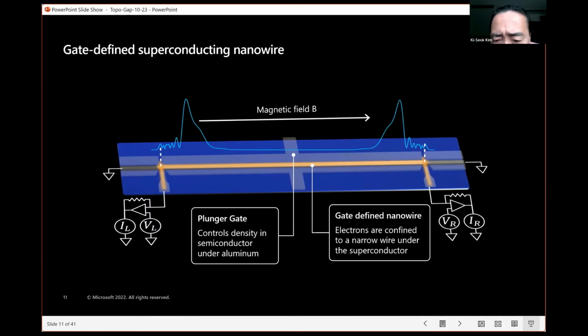Okay. Are there any questions so far? Yeah, elementary question. So I missed too. So superconductivity is assigned to aluminum. So applying gate voltage, you mentioned screening. What's the effect of gate voltage on aluminum? Nothing. There's minimal effect of the gate voltage on aluminum because aluminum is a metal and it's grounded and has very high density. So the aluminum is grounded at the sides. It doesn't really care. Its density is too high. You can't change the density inside of aluminum. You know, a big long aluminum wire. The semiconductor has much lower density, 3 orders of magnitude lower. And so with the gates, we can change the density in the semiconductor. I see. Thank you.